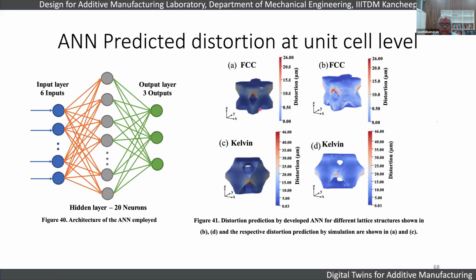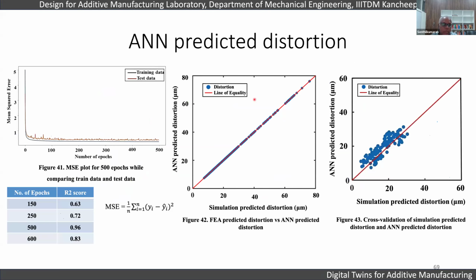Then we used the ANN predictor. This is the original distortion predicted from the commercial software, and we also used the data points and simulated that at commercial scale. This is one of the ANN predicted distortions. This is the distortion predicted by the commercial tools using FEM methods coupled with the inherent strain, right? So now you can see the line of equality, and the cross validation of the simulation versus predicted ANN distortion.